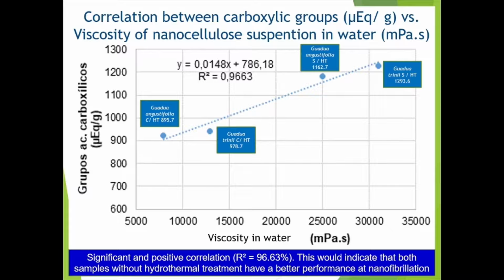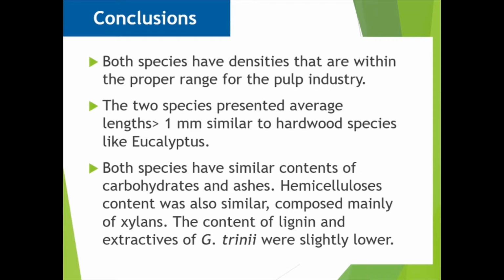In the graph, we observe the correlation between the content of carboxylic groups generated in TEMPO oxidation and the viscosity of the nanocellulose suspension in water. It presents a correlation coefficient of 96%, which indicates that the relationship is significant and positive. Since the nanocellulose from pulps without hydrothermal pretreatment is closer to the trend line, they present a better behavior for nanofibrillation. Now we are going to see the conclusions.